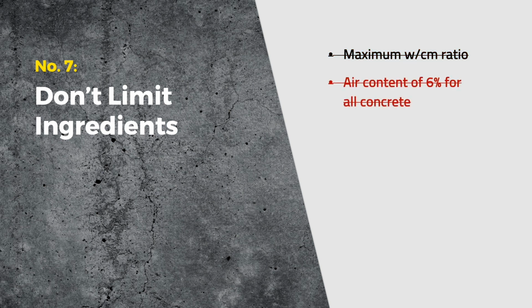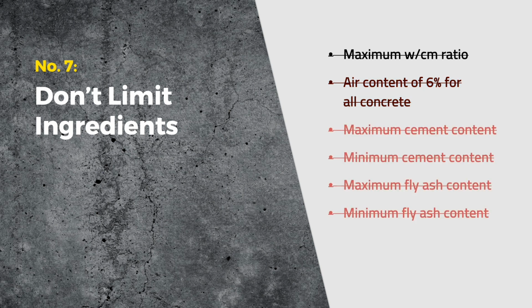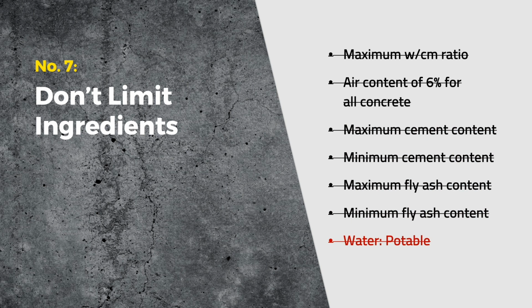The same is true for air content. It's only required for concrete exposed to freezing and thawing. Air entraining decreases concrete strength. For instance, a 10% decrease in cementitious material content for 4,000 psi air-entrained concrete compared to non-air-entrained concrete for the same strength would roughly translate to a 9% increase in carbon footprint. Do not list a maximum or minimum cement content, maximum or minimum SCM content, or quantity of admixtures. Do not limit water used for making concrete to potable water. There is an ASTM specification for water used to make concrete.